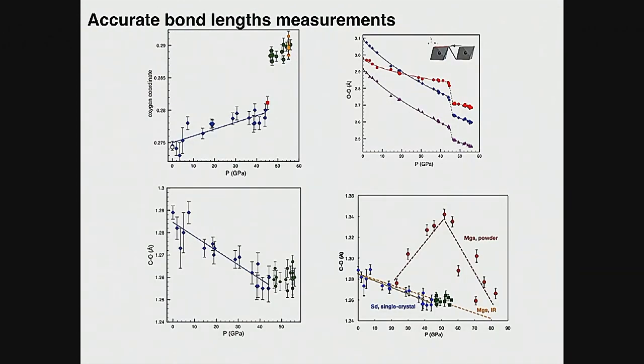And with the second data set, the first data set was not refinable. You could not retrieve good information. And with single crystal, the good thing is that you actually are confronted with that. You understand you can't refine. With powders, you have to have more judgment in understanding where you have to stop, what you can actually retrieve from those data. And I was able to chase down this deformation extremely well.